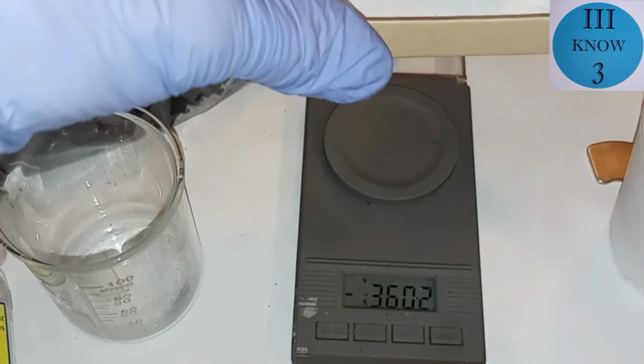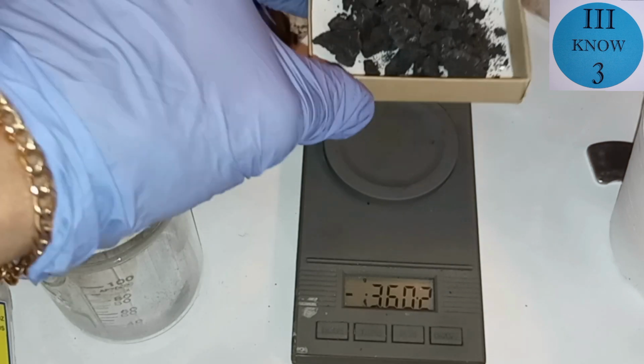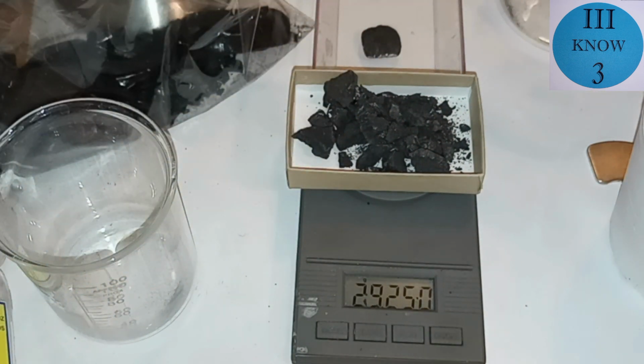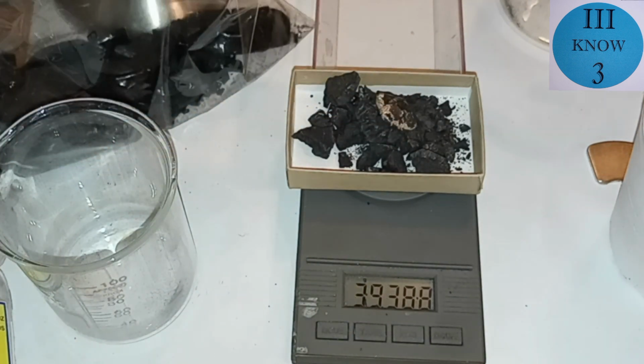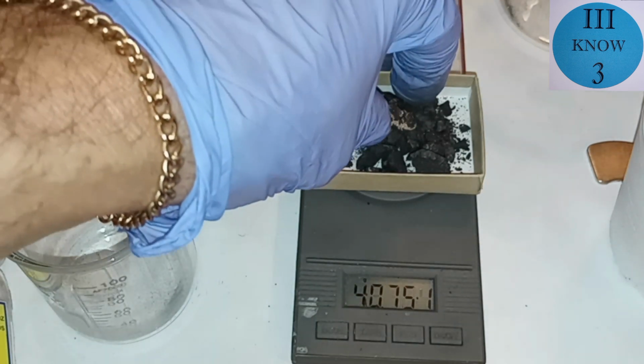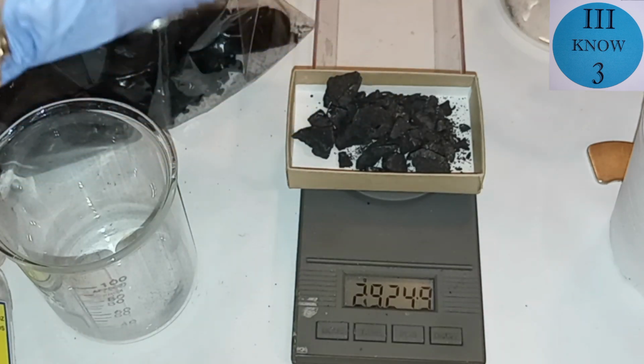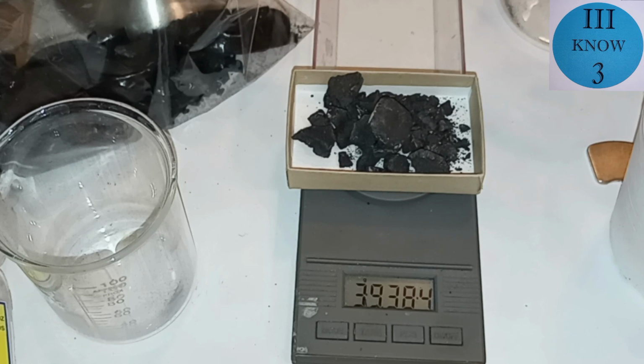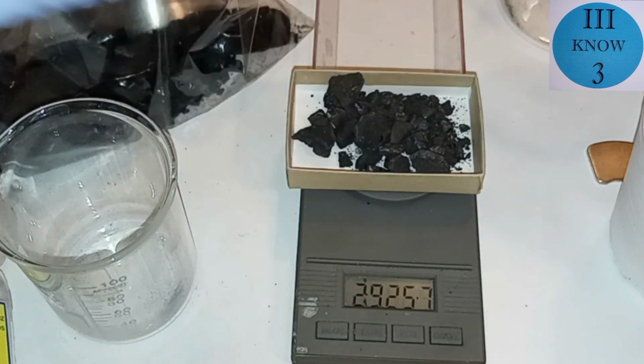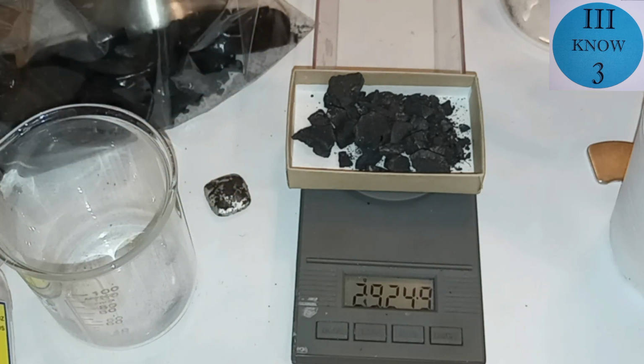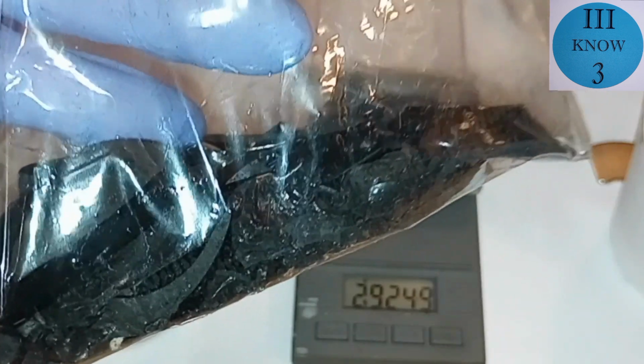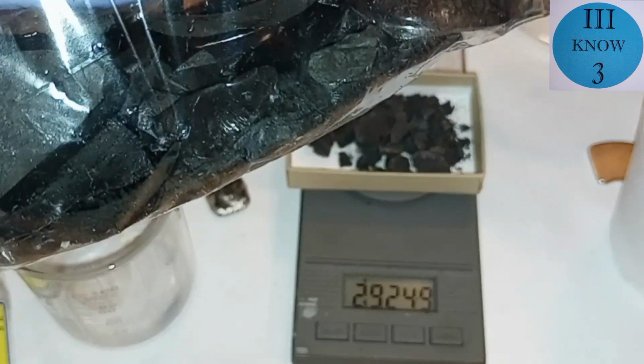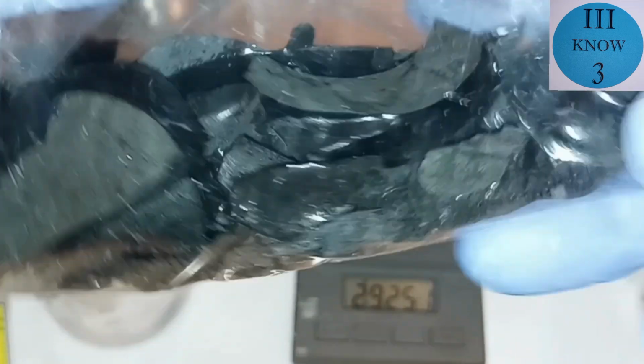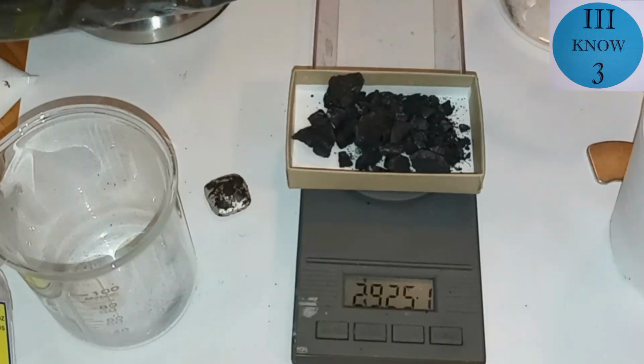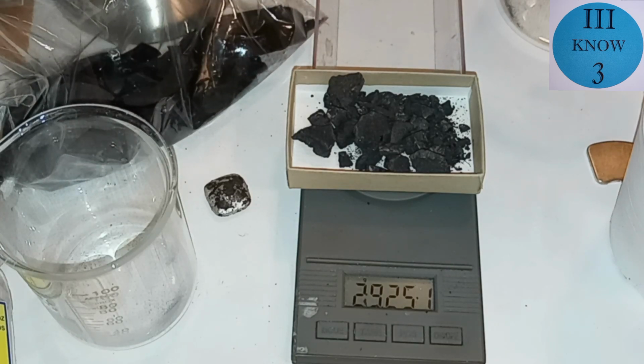So after all this was busted up, we have about 29 grams there. So that's 39.38 grams. I may have picked up a little bit of extra slag because we were only at like 38 when we got done with the melt before, but now we have about 40 grams of material. We started with 70 grams of material between the gold plated stuff and the silver that was in there, but let's say if we were down to 40, that means that 30 grams of the base metals were in here in the glossy slag. And this could possibly contain some precious metals that got stuck in the slag, but I really don't see any evidence of that in the slag itself. Although if it's microscopic, you wouldn't see it, and that's why we're saving it.